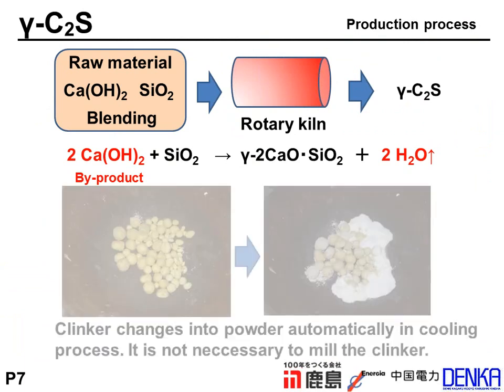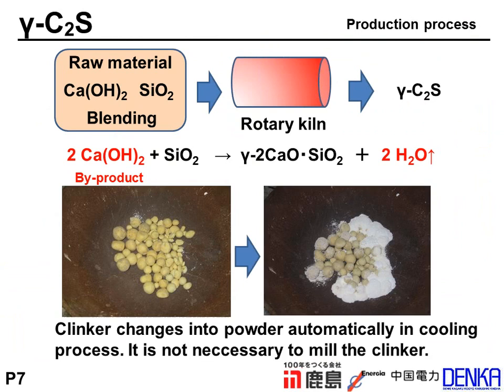This calcium hydroxide is a byproduct and does not emit carbon dioxide in calcination. It's eco-friendly. And the clinker changes into powder automatically in the cooling process, so it's not necessary to mill the clinker. Therefore, the carbon dioxide emission of gamma C2S is very low.